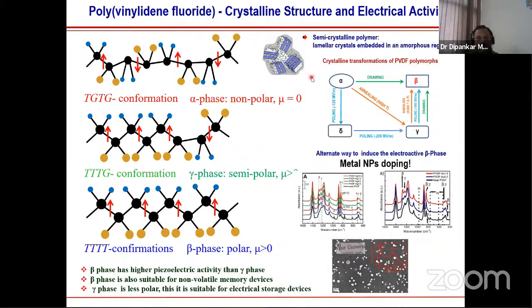And in this semi-crystalline polymer, the piezoelectricity basically arises due to the crystalline regime. So in order to get the piezoelectricity and pyroelectricity, how much degree of crystallinity there is, is one of the major factors. Okay. And once we buy this particular polymer, you have this crystalline phase, which has different crystalline polymorphs. What does it mean? That means it has different crystalline phases. So one is the alpha phase, and in this alpha phase, if you look, this is the hydrogen and this is fluorine.